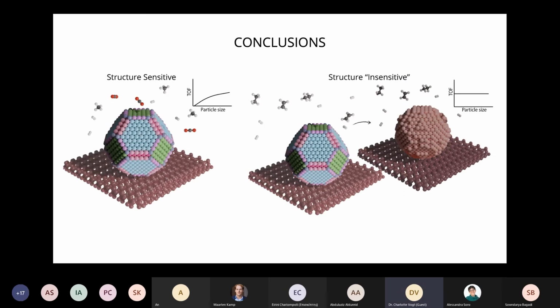So to sum up, basically what we've discussed here today and what we discussed in the article, structure sensitive reactions have a clear and clearly described dependence on the different types of sites that are available versus the different types of reactions and reaction intermediates that are there. Structure insensitivity also has that same type of dependence. However, at least for this specific structure insensitive reaction, ethene hydrogenation, the recombination of an alkyl with a hydrogen being the rate determining step, this empirically observed structure insensitivity is most likely in fact caused by the surface being the same for the different nanoparticle sizes, which changes our fundamental understanding of this concept. In fact, we proposed those reactions to be termed apparently structure insensitive rather than truly structure insensitive.